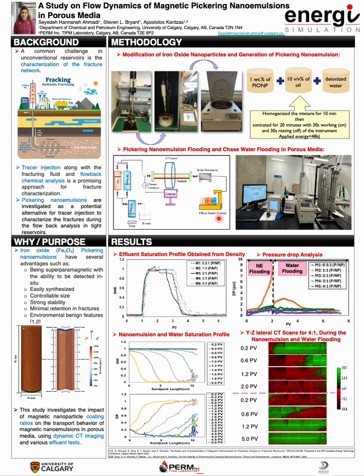In this experiment, we inject 2 pore volumes of nanoemulsion and then wash it with 5 pore volumes of water. At the beginning of the experiment, we first saturate our sandpack with water, then invade it with nanoemulsion, and then chase with water flooding. After doing the experiment, we collect all the results and then interpret all of them.